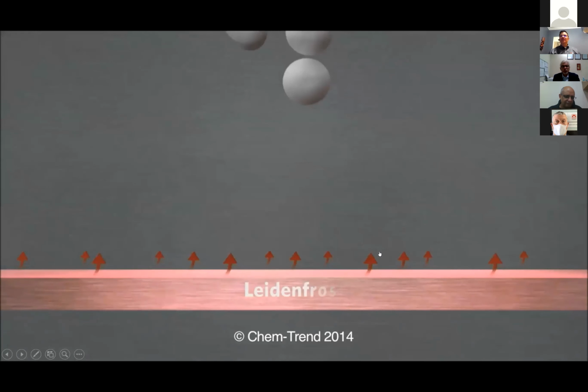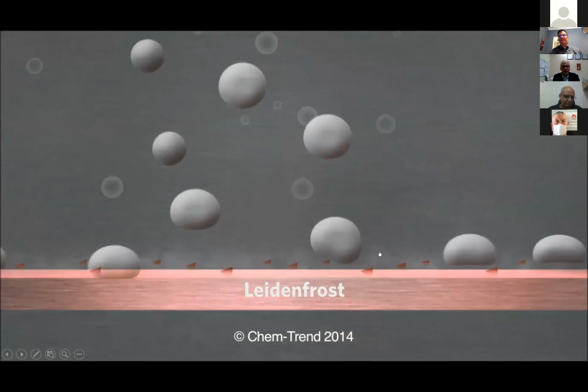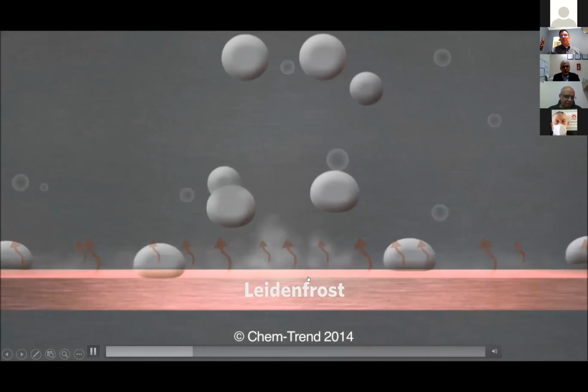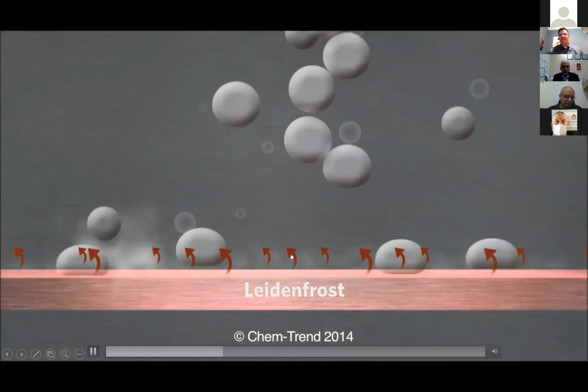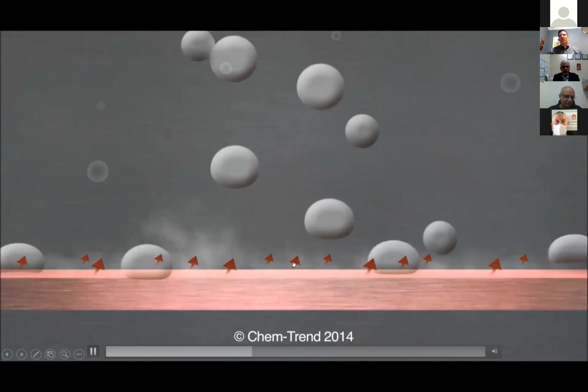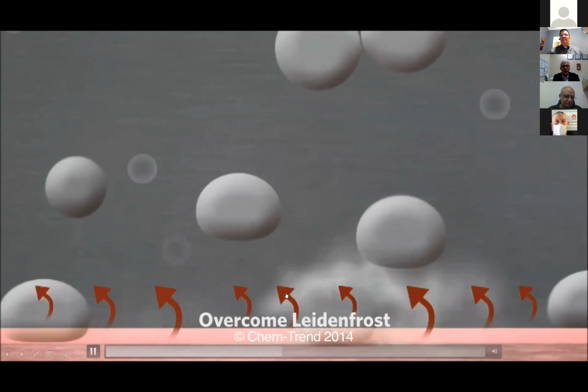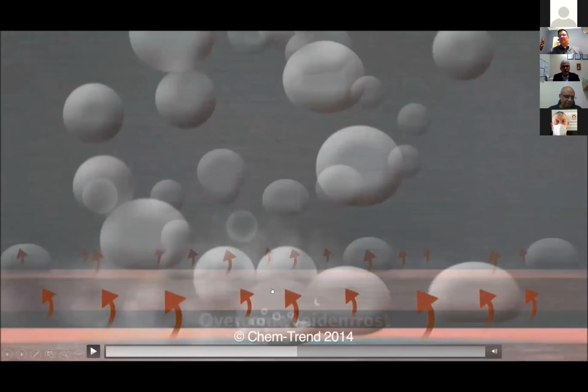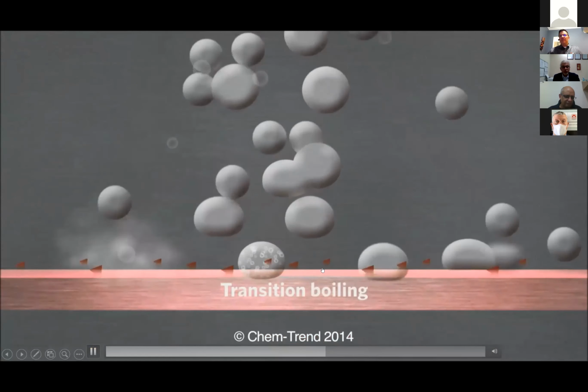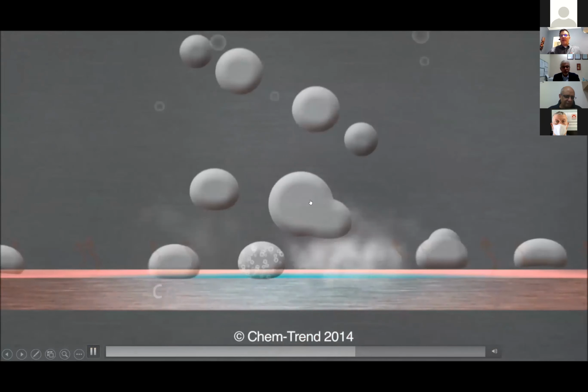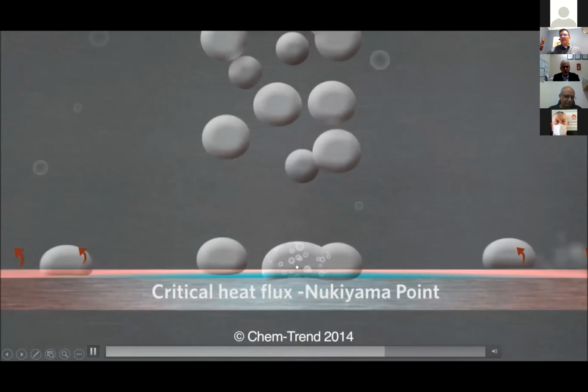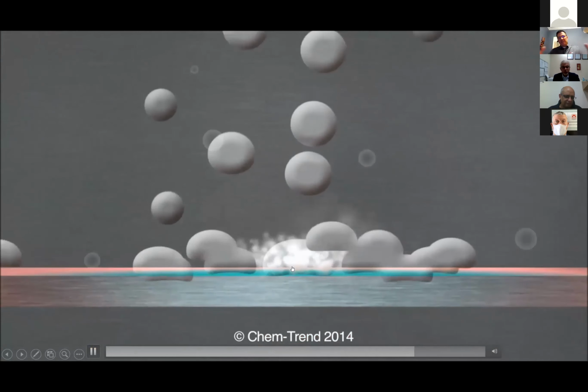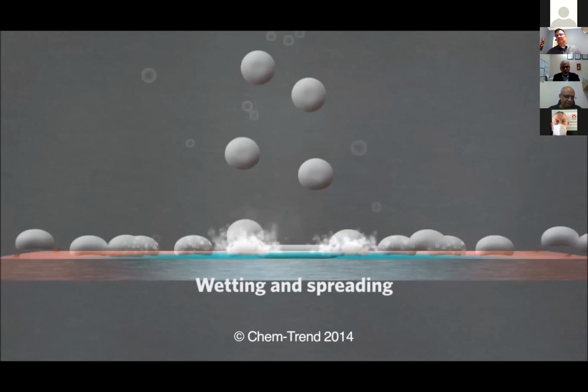Now I have some animation I'll show that should make this clearer. So we're spraying a surface, and these droplets are shown with little arrows. That's the Leidenfrost phenomenon, that vapor barrier. We're not breaking through it, and the droplets bounce off until we hit the point where we overcome Leidenfrost and start getting explosive boiling. So the die starts to cool at that point, and it's maximized when we get droplets that stay on the surface and boil—nucleate boiling. That's where we really start to get wetting and spreading of the die lubricant across the surface, building your protective film.